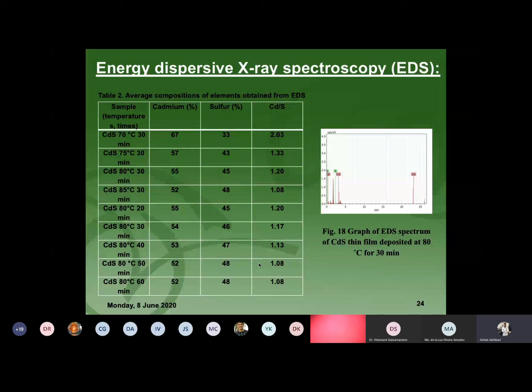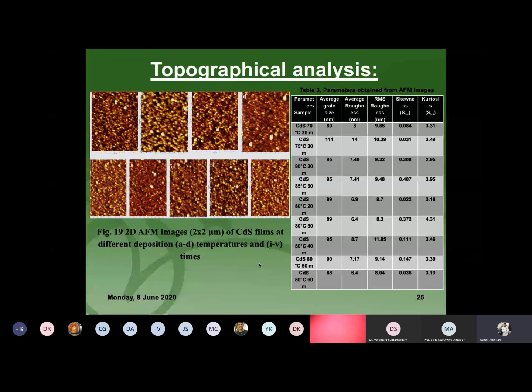For the topographical study of the film, we analyzed by atomic force microscopy. Figure 19 shows the 2D image of the film, showing a spherical structure, the same behavior as obtained from scanning electron microscopy. Even at low temperature, there is a presence of pinholes.